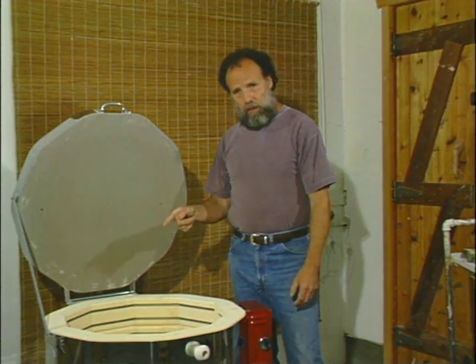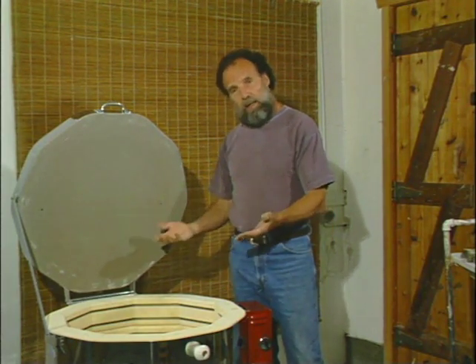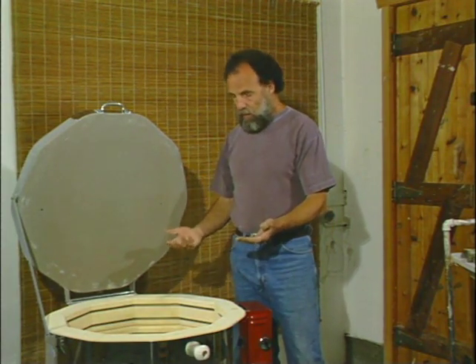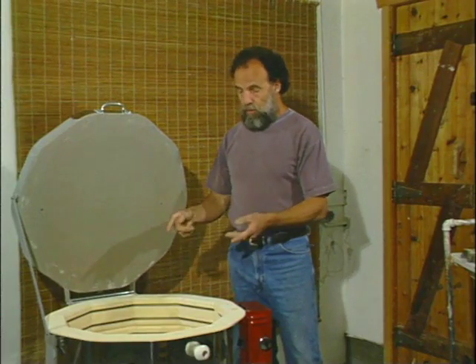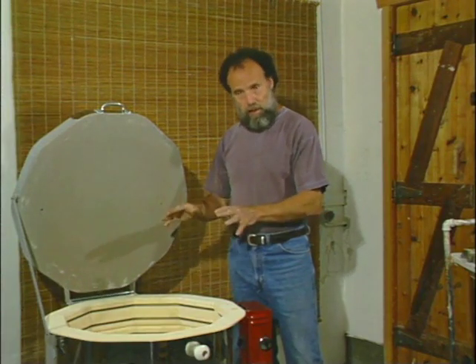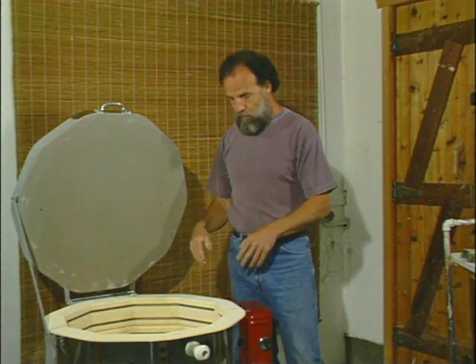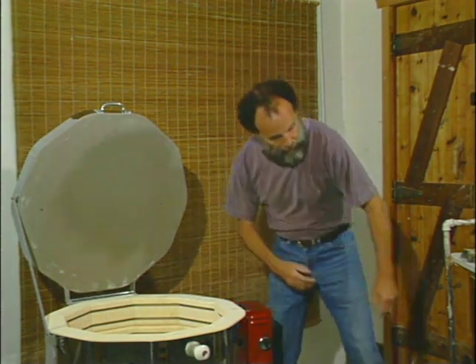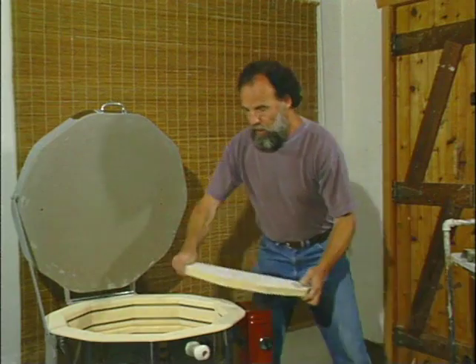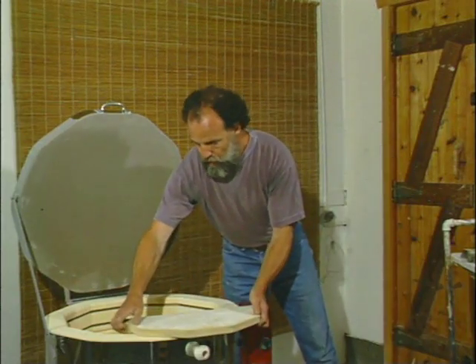Some kiln manufacturers ask that you start the stack by placing a shelf in the bottom of the kiln. This is particularly relevant, of course, if you've got an environment where you need some space underneath the shelf for the fumes to be drawn down under the stack. Now, we have half shelves, so we'll have to put in 2 of those.